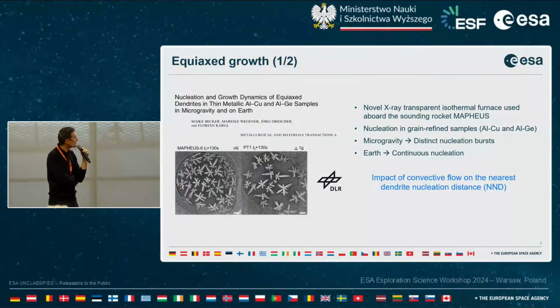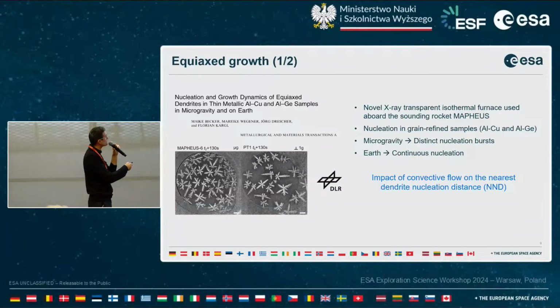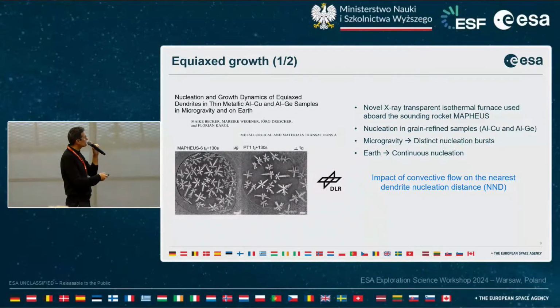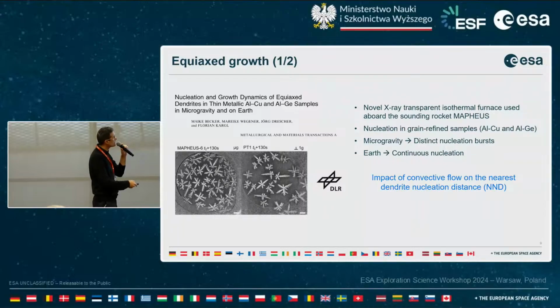microgravity. And what was observed, there was a focus on the nucleation, the formation of the new grains and how they appear and their dynamics. And what was observed is that in microgravity there were distinct nucleation bursts, distinct nucleation events during the formation of the grain. But on Earth, the propagation of the nucleation front was more continuous. And this has been interpreted as an impact of convective flow on Earth.